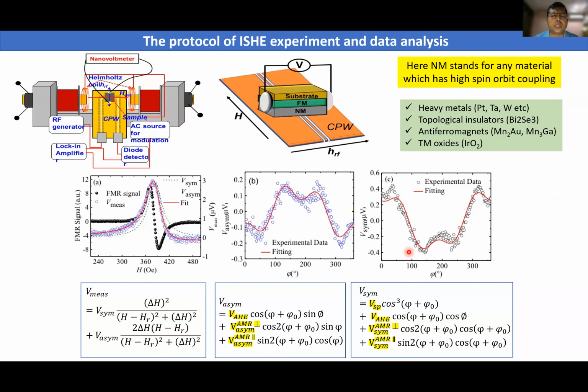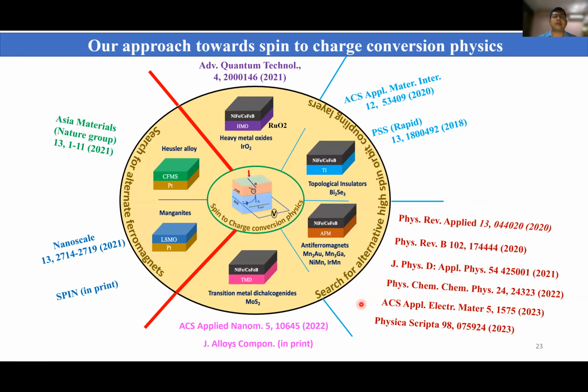So the black curve is the ferromagnetic resonance spectra, and the blue curve is the ISHE voltage. If you disentangle, you can figure out the symmetric and asymmetric voltage, and you can do angle dependent measurements to quantify different spin rectification effects like anomalous Hall effect, anisotropic magnetoresistance. But most important, the symmetric part contains the spin pumping voltage, which is our primary interest. And you can see how much is the spin pumping voltage with respect to the spin rectification effects. If it is more, that's good. And this is like a quick summary.